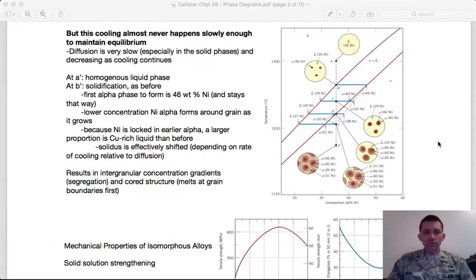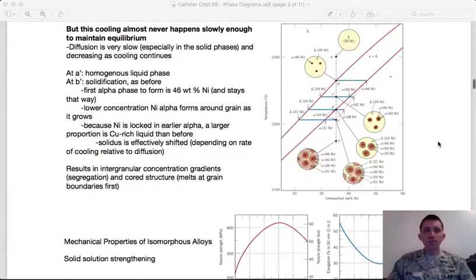especially as I cool down, right? Diffusion slows down. We saw that before. And so cooling almost never happens slowly enough to allow this equilibrium to be maintained, right? And so we get this chord structure that I alluded to before. Diffusion is slow, especially in the solid phases. And so when you first solidify, like I said above, you're getting high nickel content grain cores, and every successive layer is going to have a lower nickel content. And under normal conditions, there's not enough time and temperature for those atoms to diffuse back out, and so you end up with a chord structure.